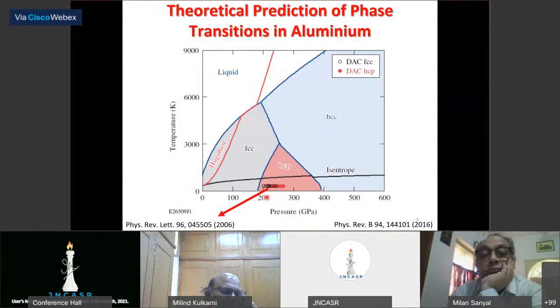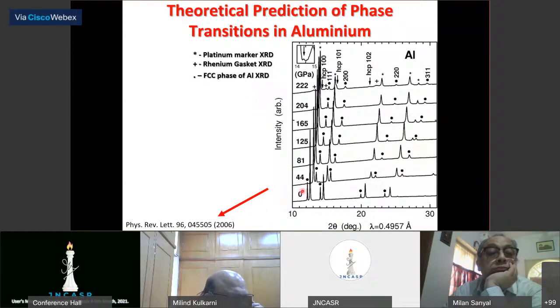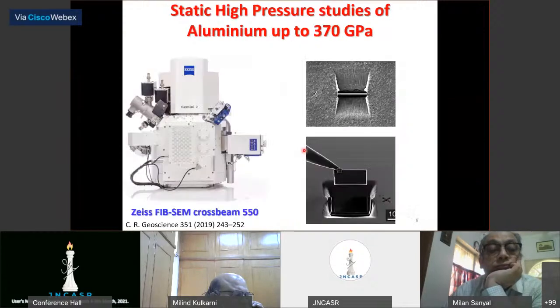But interestingly, when you look at the phase diagram of aluminum, you realize that at higher pressures and higher temperatures, BCC is the structure which is stabilized. It starts with FCC. If I take room temperature, I would see that it goes to HCP and then to BCC. And when you are doing such high pressures, you can see the problem if your synchrotron source is not very apt for it, that you will be saturated with most of the gasket peaks as well as your pressure marker peaks rather than your actual peaks coming from the system. So here it is very difficult to see the HCP peak evolving, but this is the work which was done.